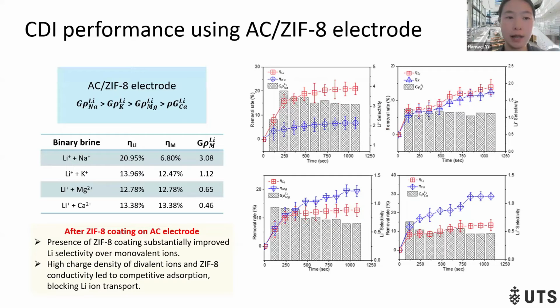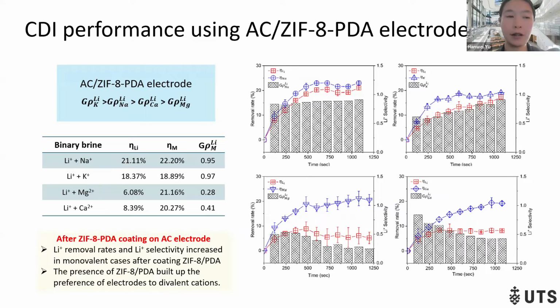After coating the ZIF8 layer, we can find that the presence of the ZIF8 coating substantially improved the lithium selectivity over monovalent ions. But the high charge density of divalent ions and the ZIF8 conductivity can lead to competitive adsorption, blocking the lithium ion transport. After modifying with ZIF8 polydopamine, we can find that the lithium removal rate and lithium selectivity increased in monovalent cases. And the presence of the ZIF8 polydopamine built up the preference of the electrode for divalent ions.